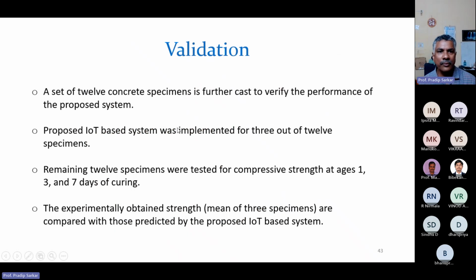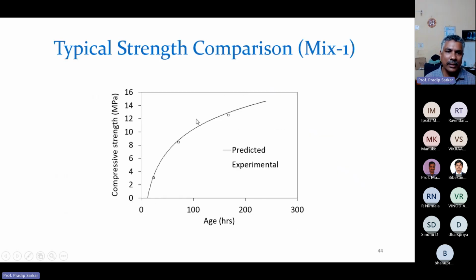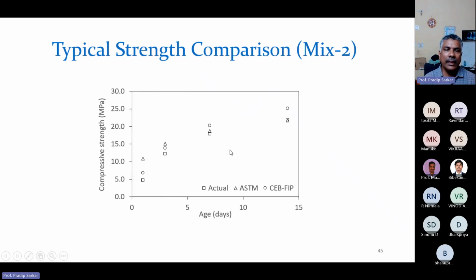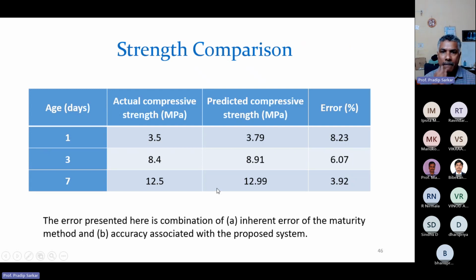For validating, after we got that data, we repeated this test and found the actual break test values. These are the predicted values as per this equation, and the experimental values are given in these small boxes, so it matches very closely to the actual compressive strength. And this is for one mix. For another mix, we again used both methods, and it gives quite good agreement with the actual strength. You can see the errors between the actual and predicted compressive strength are 8%, 6% and 3% in that range.